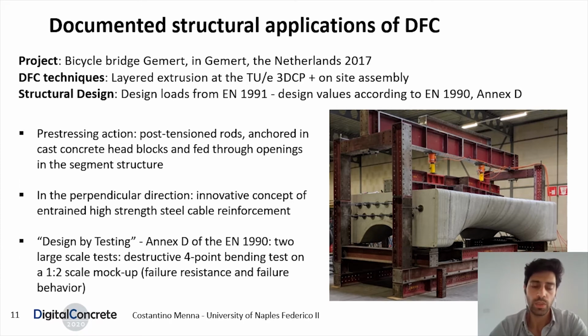Whereas in the perpendicular directions, the reinforcement consisted of an innovative concept of entrained high-strength steel cable. The global verification of the behavior of such an innovative structure was completed by means of design by testing that is compliant with Annex D of EN 1990. In practice, an experimental test was made of a mock-up structure at scale 1/2 in order to check the failure resistance and the failure behavior of such an innovative bridge.